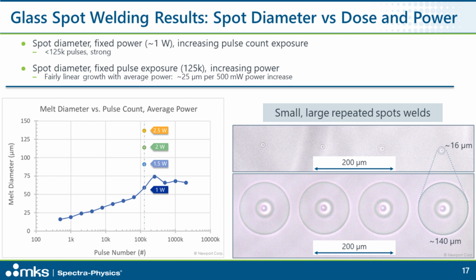So something about the melt pool that's being generated and the stationary beam is creating a little bit of instability. But what we can do is then back it off to where we have a good large melt diameter in a fairly stable regime, which is 125,000 pulses. And from there, we can increase the power. By increasing the power from 1 watt to 1.5, all the way up to 2.5 watts, which is still quite low for a 50-watt laser, we have a large increase in the melt diameter, and roughly with every half watt of power increase, we find a 25 micron increase in the melt spot diameter.